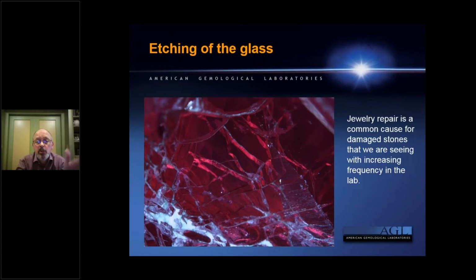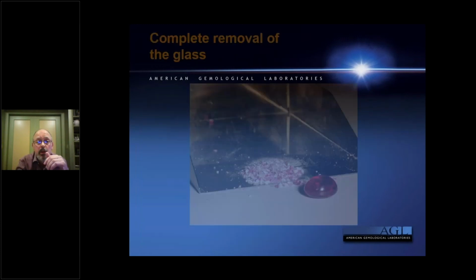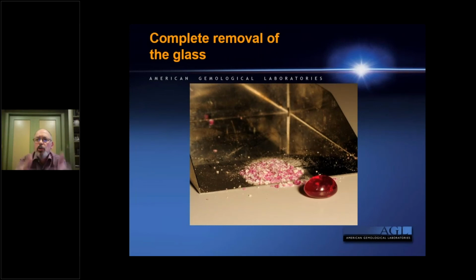And so this also led to another extent of the research that we did, and that was trying to remove all of the glass. In worst case scenarios, this is what we found. The structural integrity of the ruby was not even able to remain intact as a result of the process of removing all of this. When I sent this to someone to help me remove all of the glass, they sent me back literally powder, grains of corundum. They felt terrible. They thought they ruined something. And I said, no, this is a little bit what I expected to find. Not all composite rubies will end up like this when you remove all of the glass, but there's a significant number of them that do.